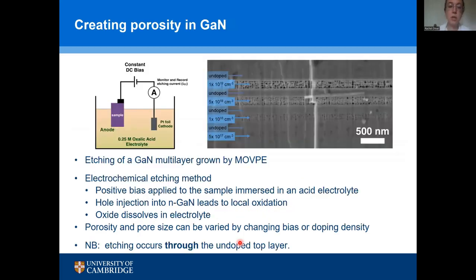So if we wish to be able to engineer refractive index, how are we going to create porosity in gallium nitride? Well, in silicon, electrochemical etching was used, and here we take a similar approach, an electrochemical approach. Our electrochemical process developed in Cambridge uses oxalic acid as our electrolyte, as our etchant. Our sample is the anode in an electrochemical circuit and platinum is our cathode. So we're going to have current flowing through the electrode, through the electrolyte and round this circuit.